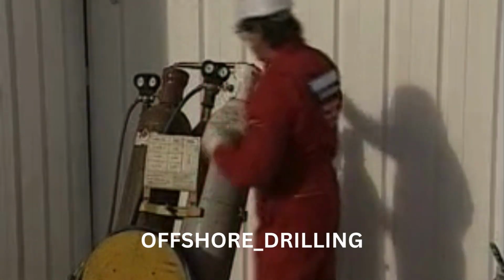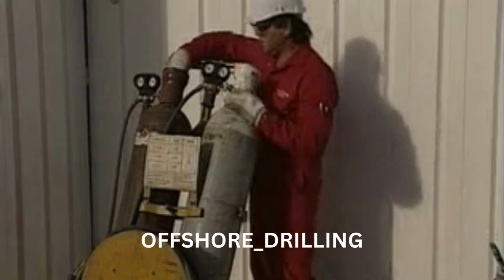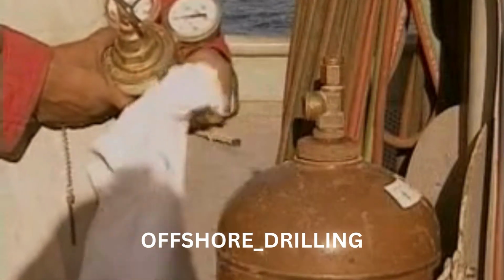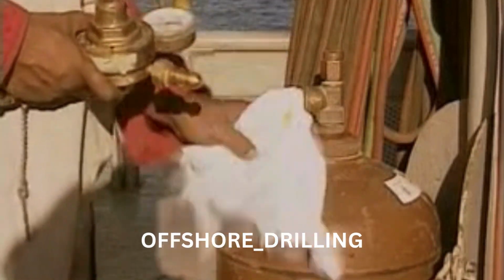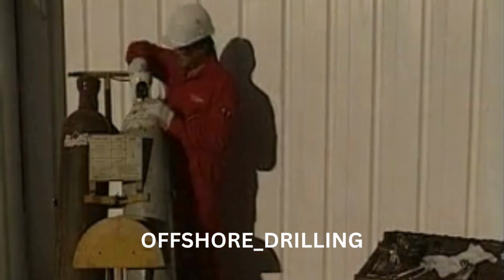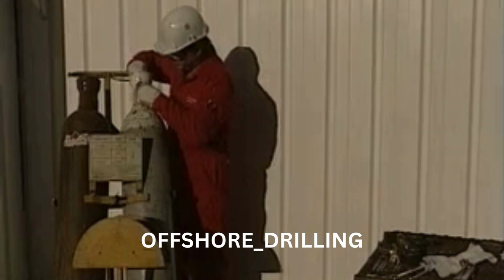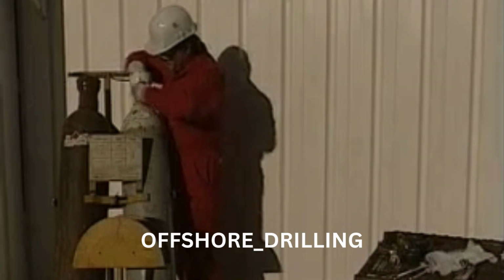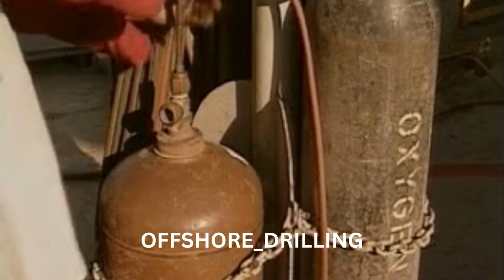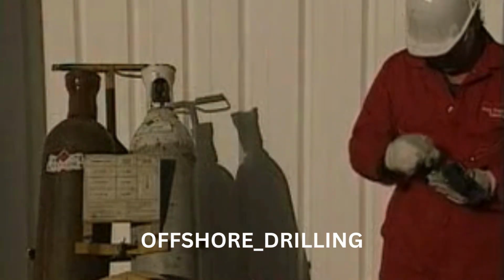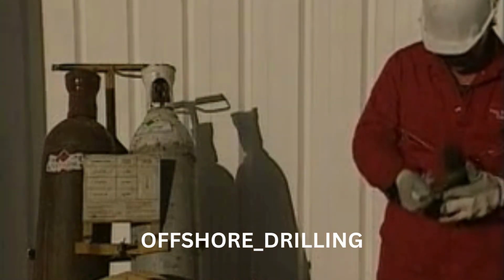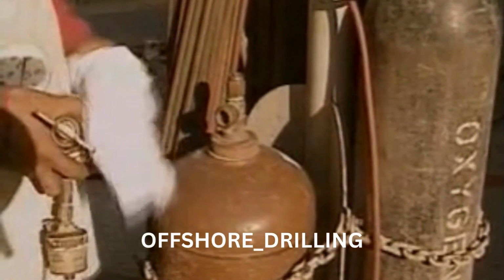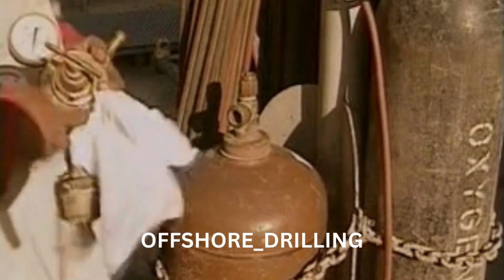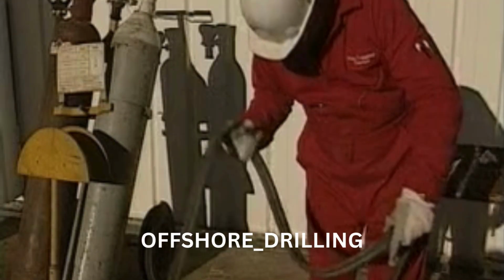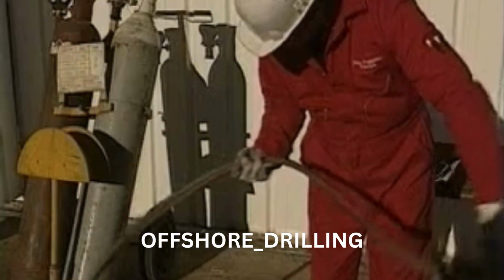There are a number of checks you should carry out on the equipment before any job. Begin by cleaning the cylinder valve of any oil or grease. Make sure there are no sources of ignition in the vicinity. Then stand to one side of the valve and crack the cylinder briefly to blow out any dirt. Inspect the regulator for signs of damage and make sure it is clear of oil and grease before fitting it to the cylinder. Before fitting the hoses, they should be checked for cuts or burns.